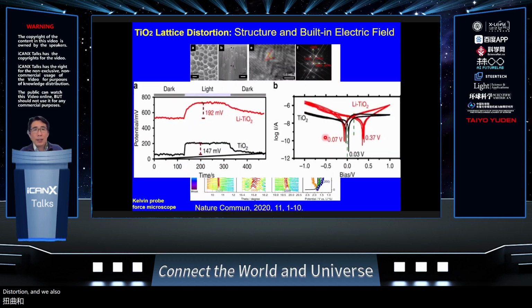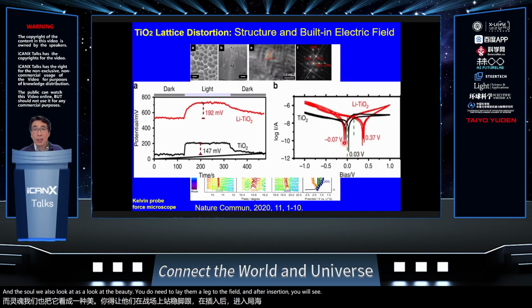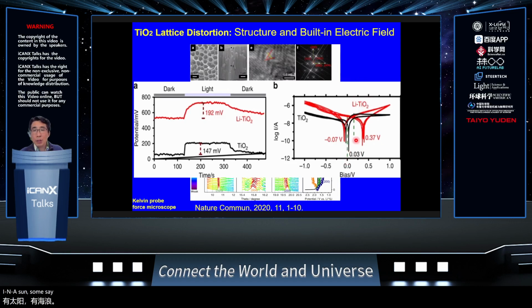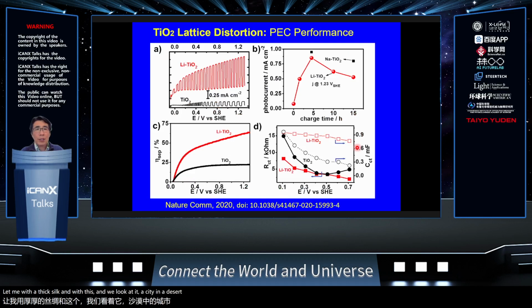We also applied surface potential difference measurements to understand the structure change. After we insert the lithium species into the structure, the surface has more photocharged holes accumulated. We also looked at the built-in electric field, and after insertion we see there is certainly some electric field generated in this 7 micrometer thick film. And when we look at the photocurrent generated, after the insertion the photocurrent is several times larger than the TiO2 without any insertion.